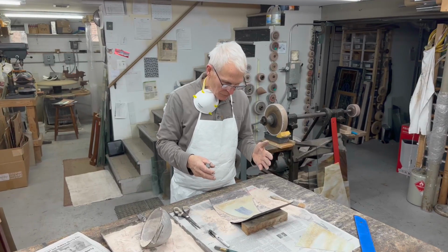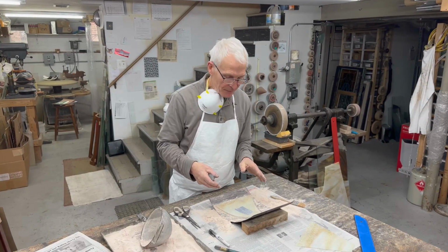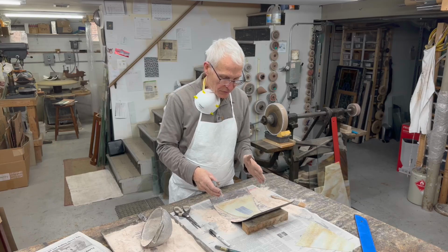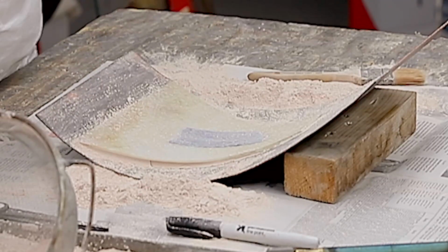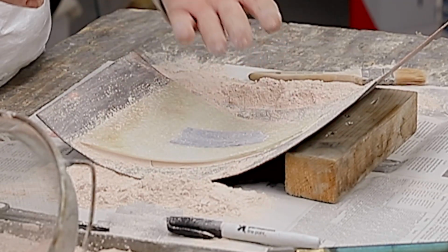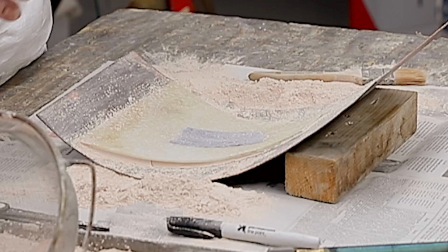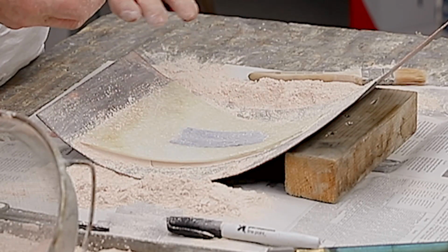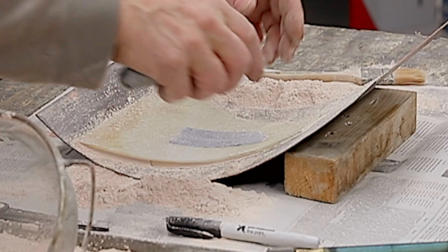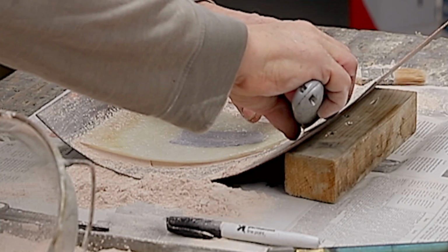Well, it's a little late now, but if you decide to do a mold like this, make sure that the glass on the front side is free from any grease or anything sticky, because that will pick up the powder, and when you peel the glass off, it's going to take it with it.